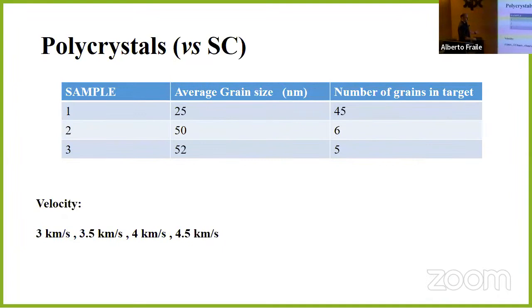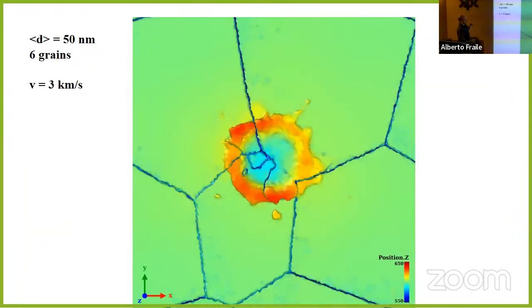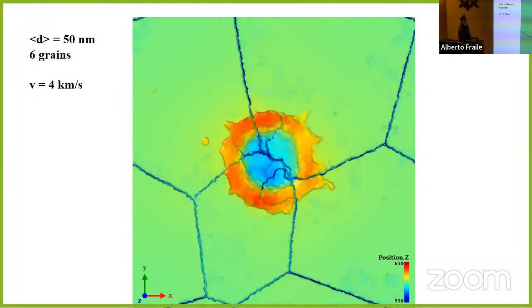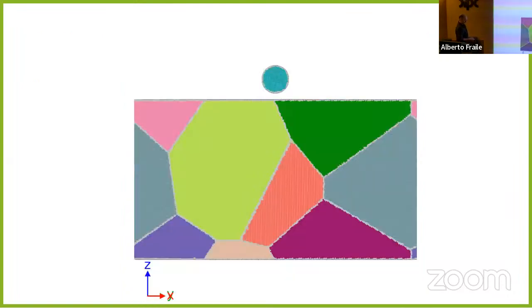But in general, doing a little bit of a systematic thing, we have now 3 different samples with this average grain size, so this number of grains. When you decrease the number of grains, the average, you have a lot of grains. When you make them big, you have few. And we did, again, for velocities. And if you look at the crater from the top, you see differences. And for example, here you see cracks in this crystal, and this is more clear when you do it at 4 kilometers per second. But in general, it looks like the same, the semicircular and everything.